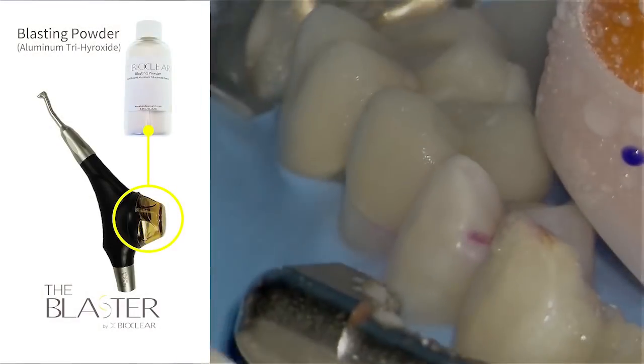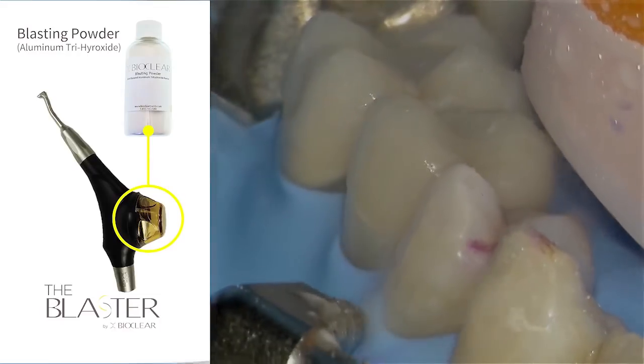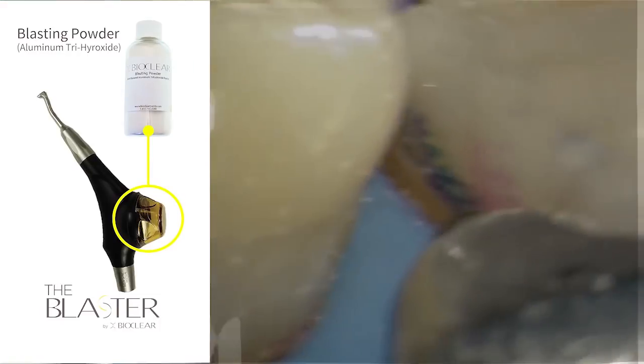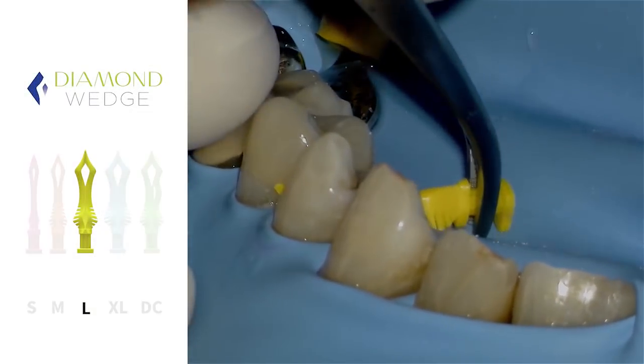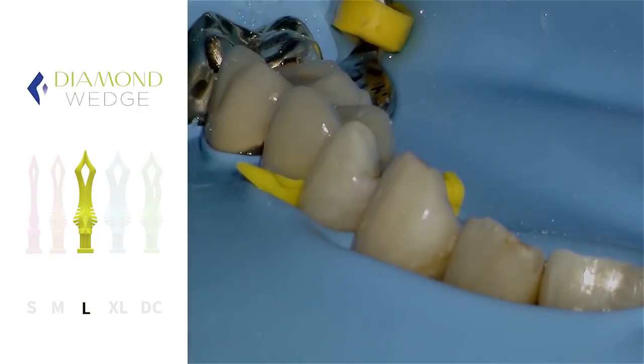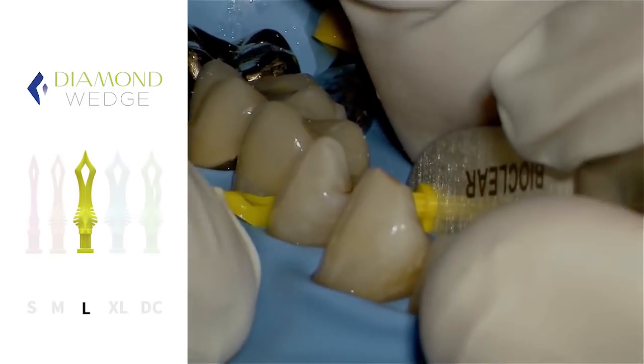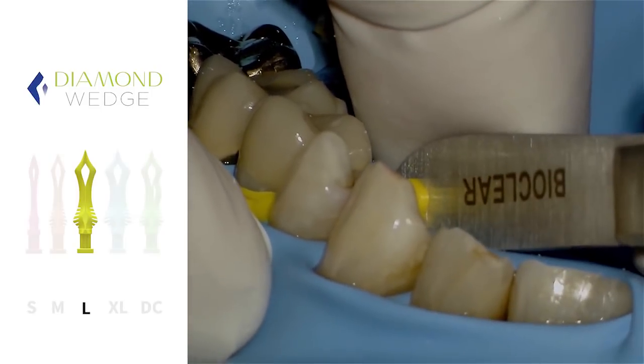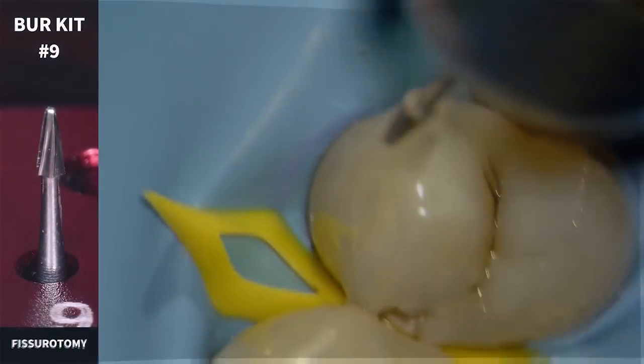So if we're going to have an infinity edge, we have to go in, disclose so we can see what we're doing, and then blast this. This is a BioClear blaster with aluminum trihydroxide. We feel that the number one reason that composites are staining is because in the area that's the infinity edge, or what other people call flashing, you cannot remove biofilm with phosphoric acid. And so the composite never bonds, turns brown right away. So anyway, we did the blasting.